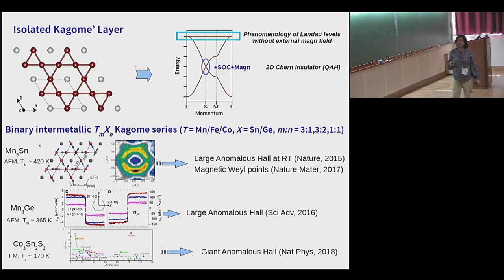And what are the corresponding material candidates? A lot of attention has been focused on this binary intermetallic Kagome series, where the T is the transition metal with the following choices, and at the X you can put either tin or germanium, and the M and N can actually have many different kinds of ratio. And these compounds show interesting features that come from the 2D Kagome layer, which is basically constituted by such transition metal sites and the spacer atoms, and that is manifested in terms of Dirac-like features, large anomalous Hall at room temperature, magnetic Weyl points, and so on.